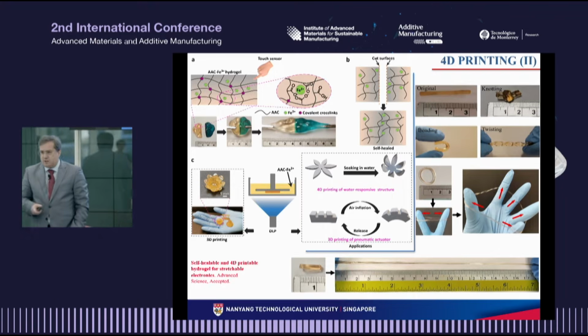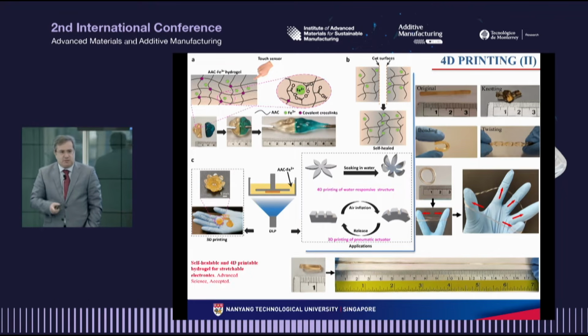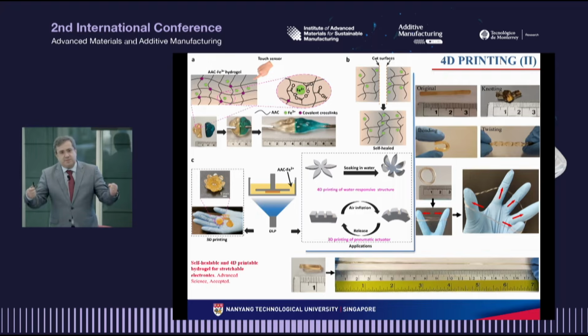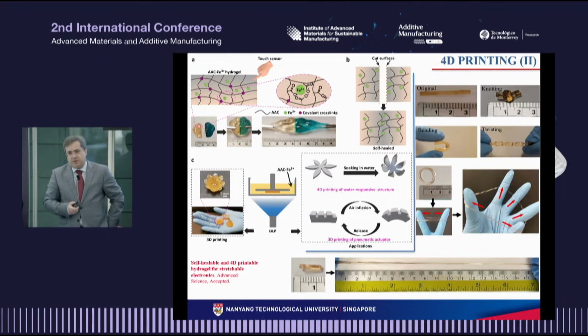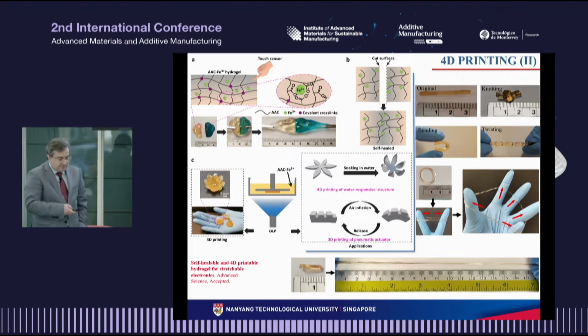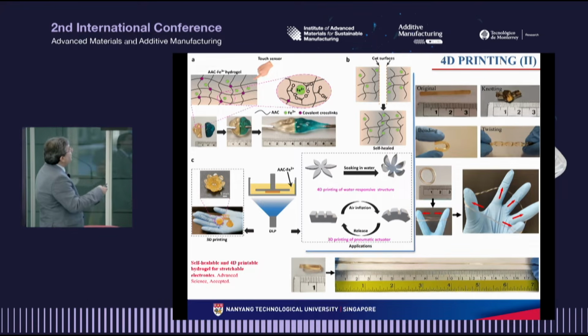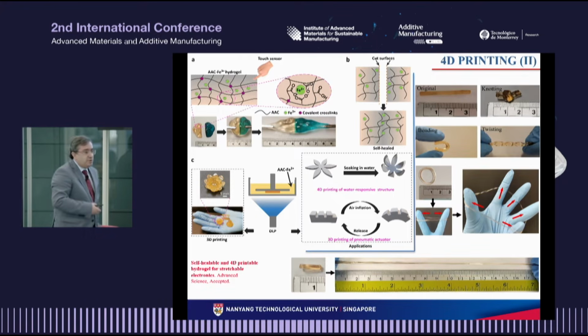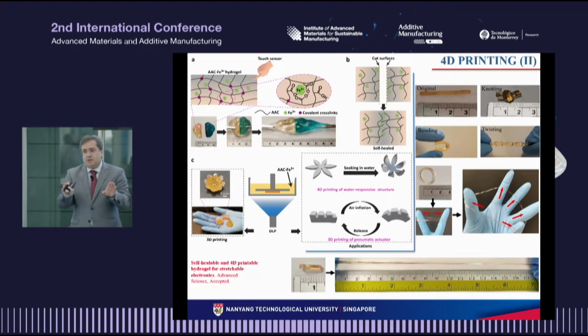We tested the hydrogels, bending, twisting, stretching, and the results show super stretch stability. So it was possible to stretch the material 17 times its original size. The materials also show self-healing, and we demonstrated that by cutting a single component into pieces and then putting the